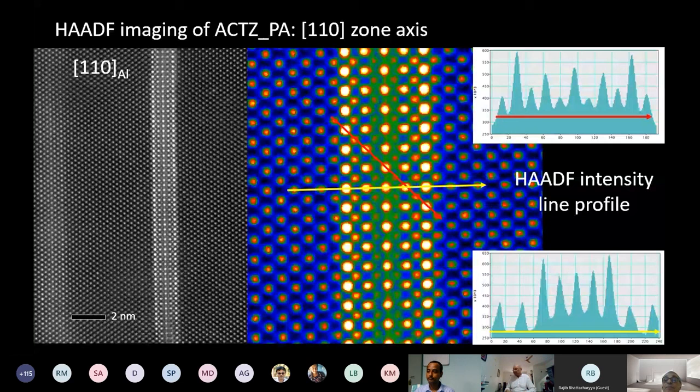But no zirconium here, because zirconium doesn't go to the theta prime precipitate. But the outside row is tantalum. As you can see, the strong peaks are tantalum, these peaks are copper, and the inside ones, the small ones, are aluminium. So you can establish that tantalum segregates at the interface of theta prime, and therefore theta prime does not coarsen, and therefore it retains its structure and coherency, and therefore it imparts the high strength.